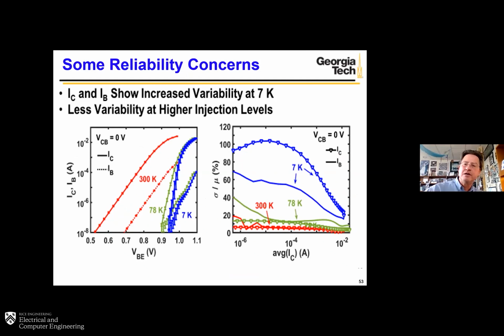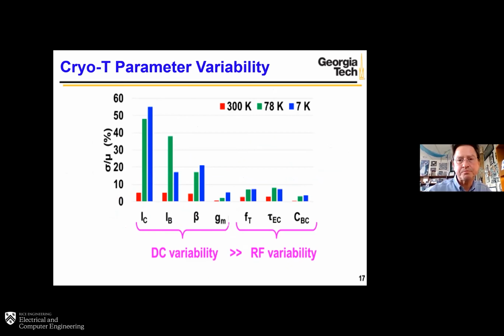And I'm going back now and measuring lots of different devices. And you see as you go down in temperature to 7 Kelvin, the error bars of scatter of those device parameters, the IC and IB, increase in variability. So if you look at the variability and plot sigma over mu in percent, you see large changes in DC variability as I go down in temperature. Which, if you think about an analog circuit, for instance, which might depend upon device-to-device matching, that's a serious issue.